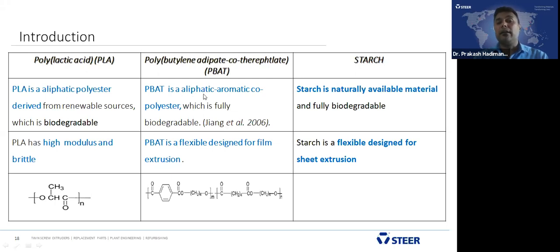PBAT is an aliphatic and aromatic copolyester. It is 100% biodegradable, and has better elongation but lower tensile strength and flexural modulus. If you want to have both, then we need to blend PLA and PBAT to get the required mechanical property. And starch is naturally available, for example corn starch and rice starch. There are many. It is 100% biodegradable, and also gives better elongation and flexibility.